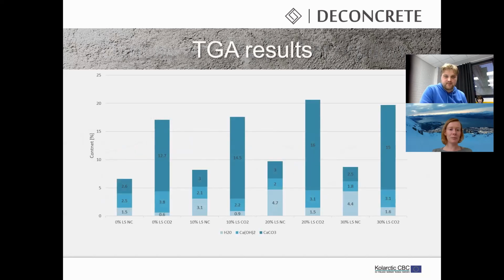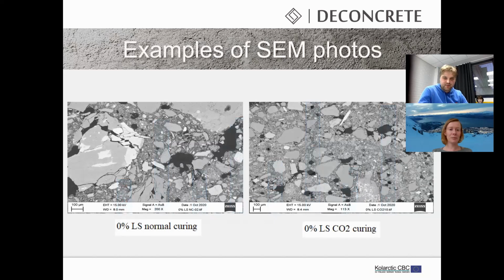And here is the TGA, thermogravimetric analysis, for the granules, to study the calcium compounds. We can see that the amount of calcium carbonates increases when carbonation curing is used. So I think these results prove that the carbonation reaction really happens in the granules. And here are some microscopic images of the surfaces of the granules. We can observe that with zero ladle slag, like normal curing, there are many cracks in the surface, and compared to the carbonation, the matrix is much denser, and those granules were also the stronger ones.